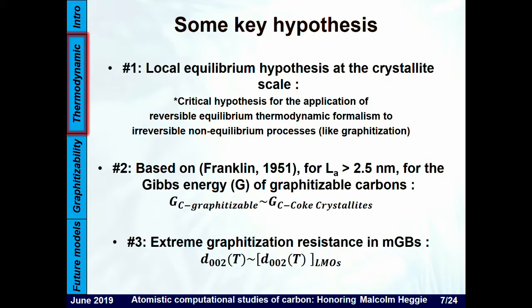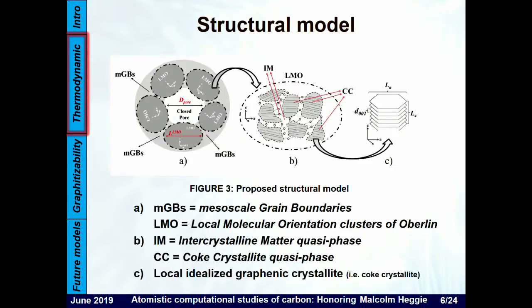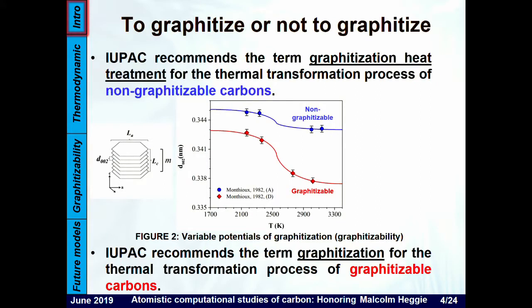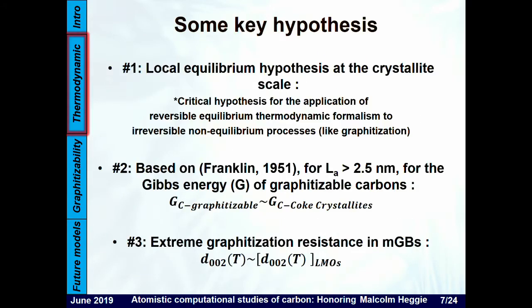The second hypothesis is that the Gibbs energy of a graphitizable carbon is, for a sufficiently large La, solely defined by the Gibbs energy of its composing crystallites. And finally, if you look at the D002 function as a function of temperature, which I showed here, we suppose that it's only defined by the change in structure inside the LMOs. So the MGBs are composed of defects which are frozen and which will never graphitize. Any graphitization only proceeds in LMOs. So these are the three main hypotheses which define the rest of the work.